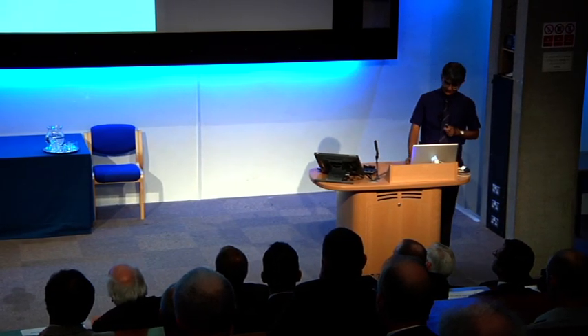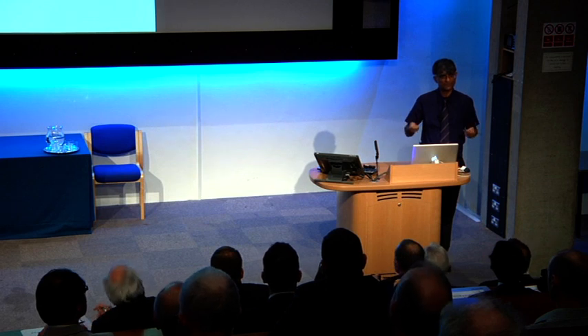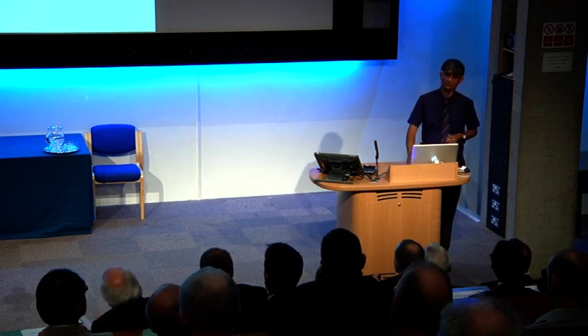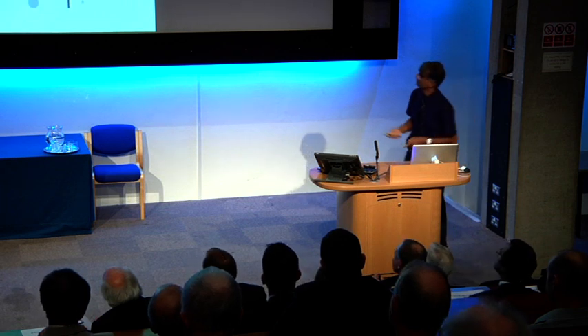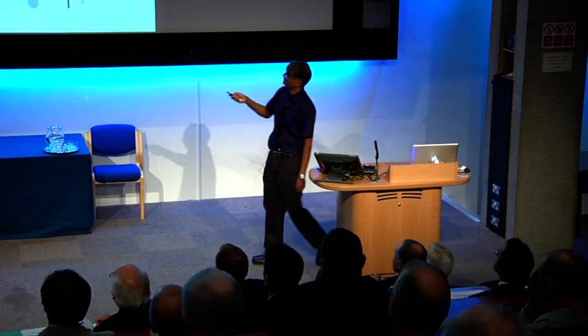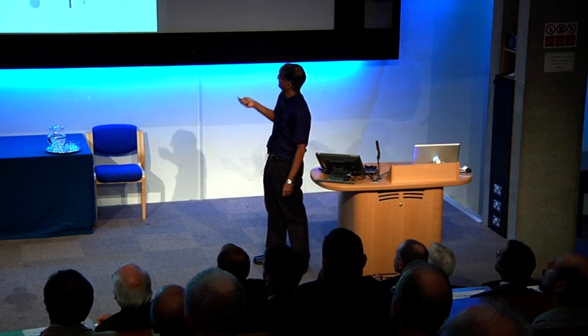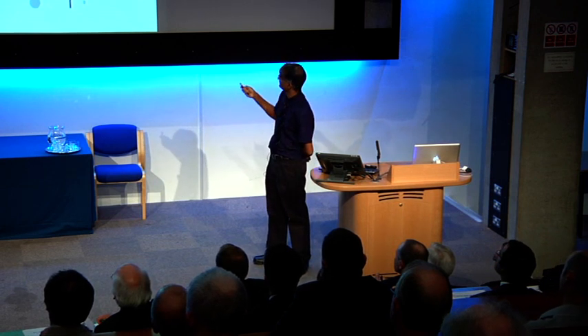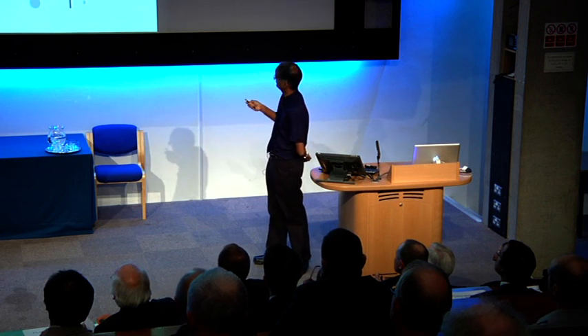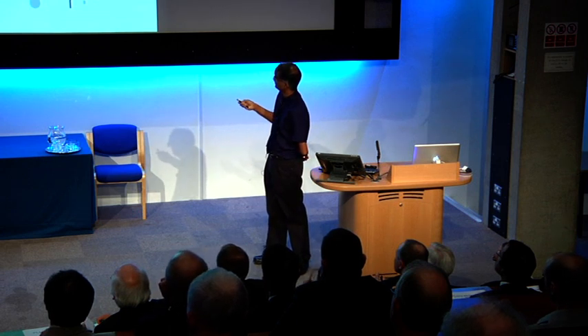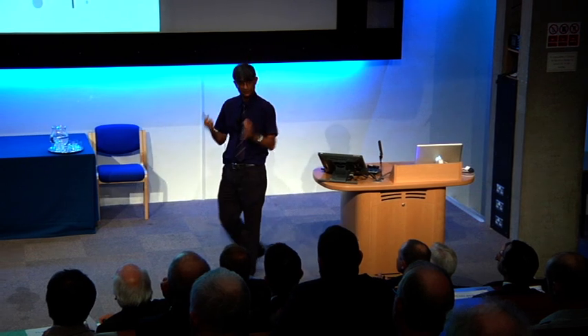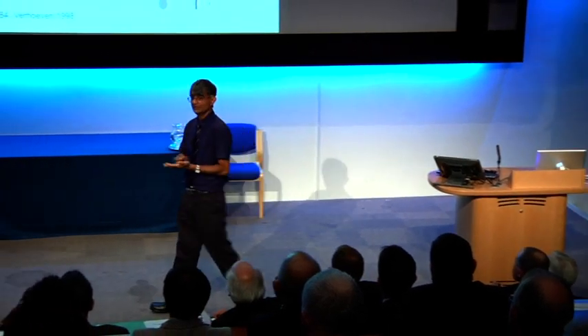So what we need is for these alternating layers of cementite and ferrite to become divorced and form particles when the austenite actually transforms at the eutectoid temperature. So conventionally, it transforms into this structure where we have these layers of ferrite and cementite. We want this to happen instead. So if we start with some cementite particles in the austenite, it's possible for the transformation front to simply move and for those particles to grow without actually establishing a cooperative growth between ferrite and cementite.